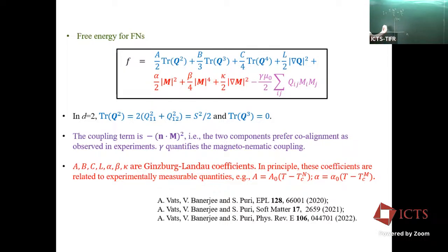For a plus sign out there, you have a parabolic free energy that's above the critical temperature. And for the minus sign out there, you have this broken symmetry free energy, where you now have 2 minima at non-zero values of the magnetization. So that's for T less than Tc. The reason I've written this down is because one is going to encounter many variants of this in the talk. So it's good to have it on the board. So that is just the vector version of that Landau free energy. This is the Ginzburg term, which penalizes the variation of the order parameter. This is something one standardly writes out.